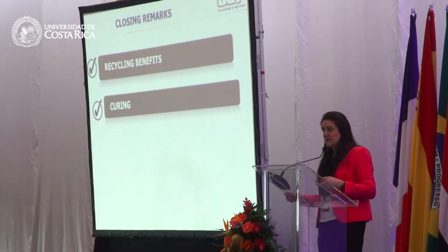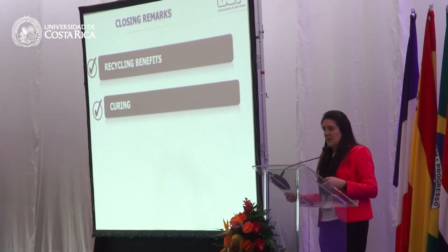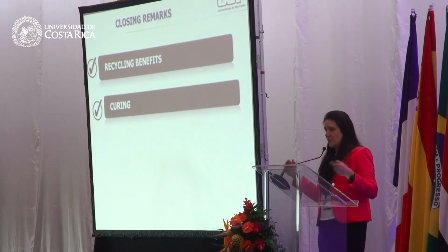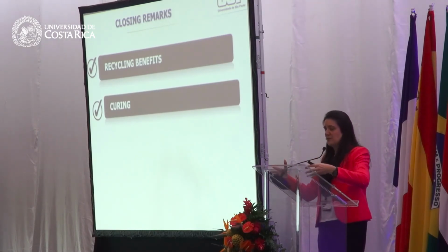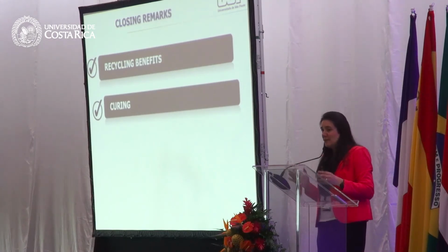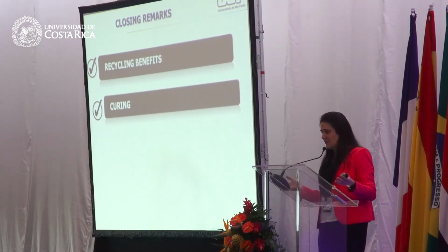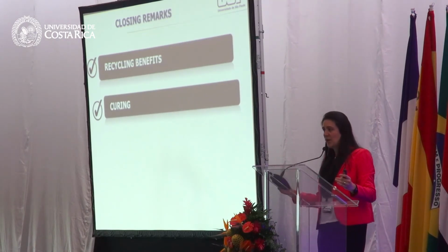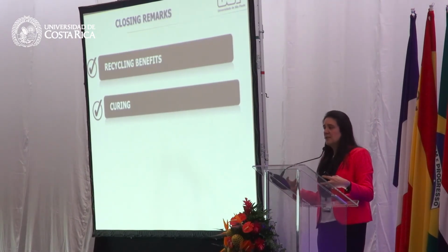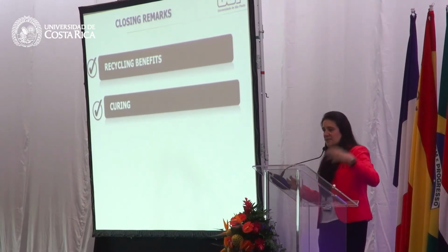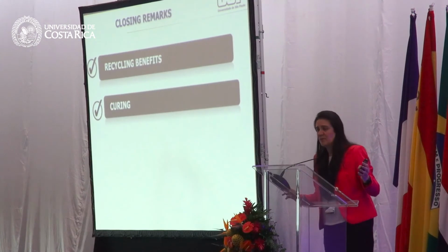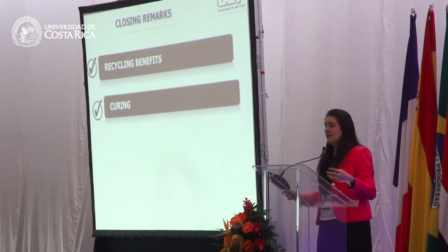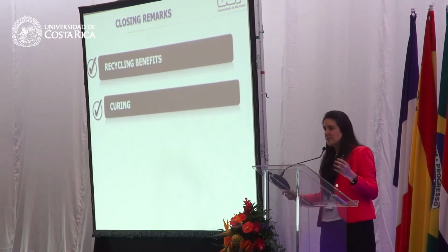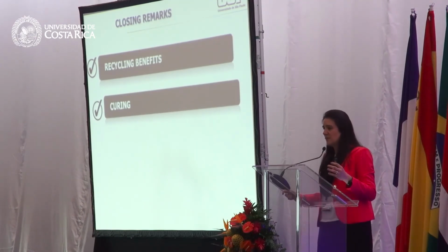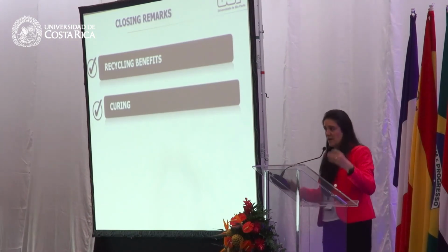We cannot neglect the curing process. We believe now that if you put this mixture in the field, the main issue at the beginning might be permanent deformation because the curing process didn't happen. So stiffness is very low. We still have water inside. After a year, if this water is not there anymore, if the curing process really happened, maybe you have to consider that this mixture may be under fatigue at a certain point. It's going to depend on the stress distributions in this pavement.